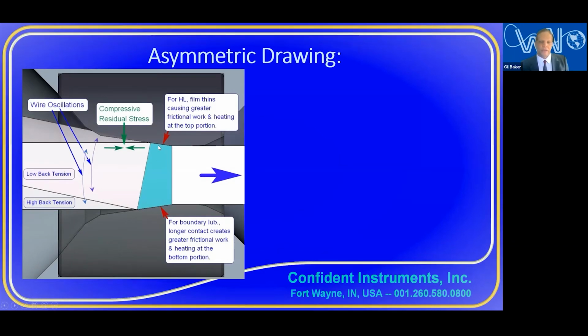And this causes issues. For example, if you have hydrodynamic lubrication, you'll have greater friction and pressure here. In other words, hydrodynamic lubrication creates a film, and the pressure between the die and wire is going to dictate the thickness of that film. But here, you're going to have higher pressure. Here you'll have lower pressure, but longer frictional contact. So actually both surfaces can be bad, but this is especially bad for hydrodynamic lubrication.